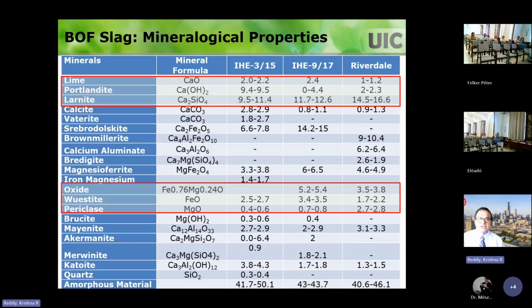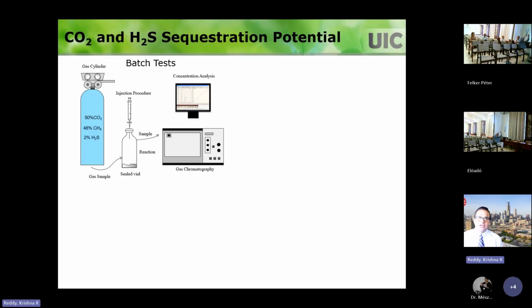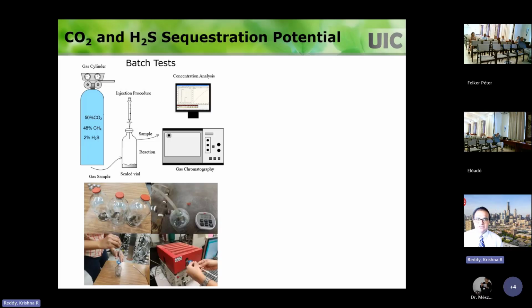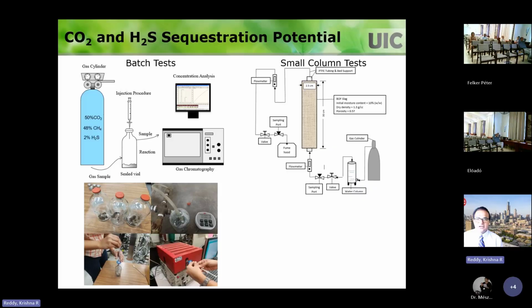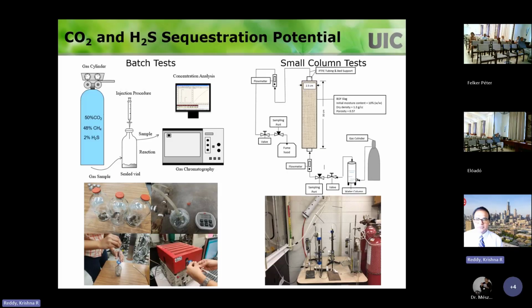So you really need to do this analysis before recommending any slag for these kind of applications, because you need to have enough calcium and enough iron so that they can react with CO2 and the H2S. To check whether this happens or not, you can do simple batch experiments, or you can do column experiments, right? Small column experiments. You don't have to have a large column. You can do the small column for this material testing.